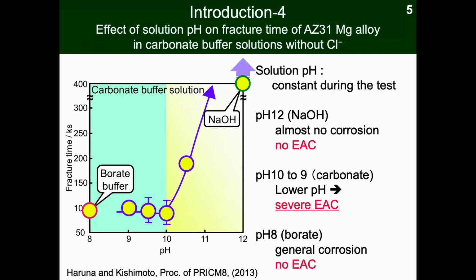So I tried to investigate the EAC behavior of the AZ31 magnesium alloy in carbonate buffer solution without chloride. And here is the effect of the solution pH on the fracture time. I recognized the solution pH is constant during the test, and severe EAC susceptibility is obtained at a pH from 9 to 10.